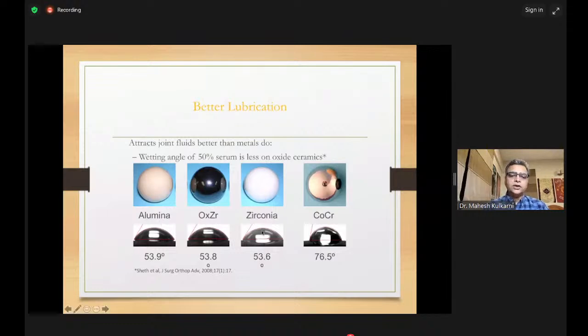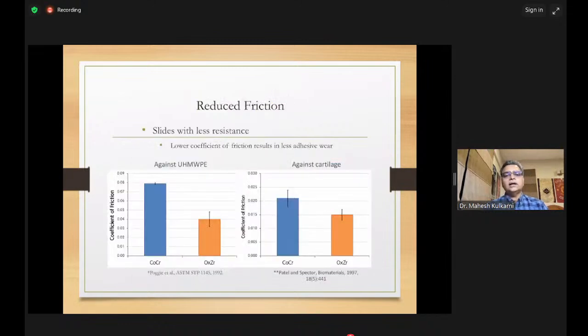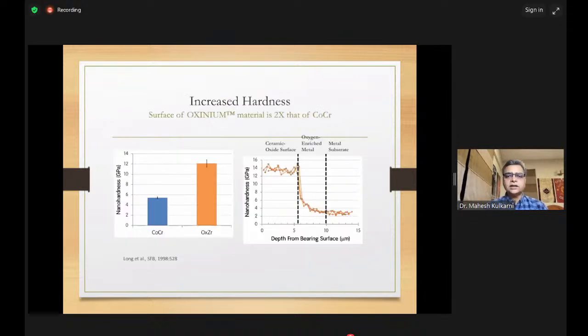As I mentioned to you, if you compare the drop on cobalt chrome, it remains, it's not very hydrophilic, that material. But if you see zirconia or oxidized zirconia or ceramic, you can see the drop actually spreads in a wider circle, and that allows you to get fluid film lubrication. Oxidized zirconium again reduces friction against both ultra high molecular weight polyethylene as well as against cartilage.